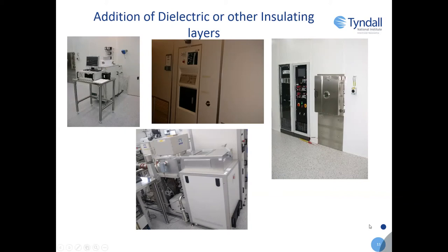So we have plasma enhanced chemical vapor deposition, that's PECVD. It's a process that typically takes place at about 300 degrees. We have a variety of these systems across the clean rooms. Some of them can also add dopant to your insulator to change the properties of it. For example, you might have silicon dioxide that you want to change the refractive index of, so you might add some boron or some phosphorus. You might want to change the melting point, so you can add those dopants and lower the melting point of your oxide. So I suppose dielectric deposition is quite varied, and you can change the stress of the layers, which people need to do sometimes to compensate for stress in other layers to keep their devices planar.